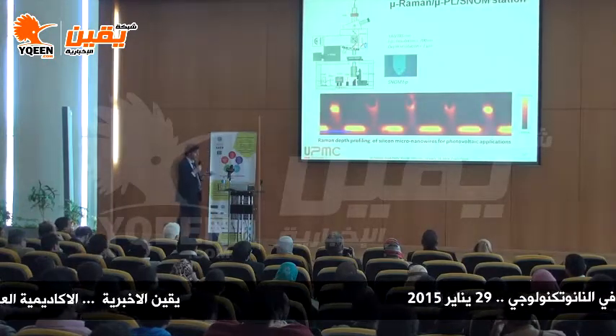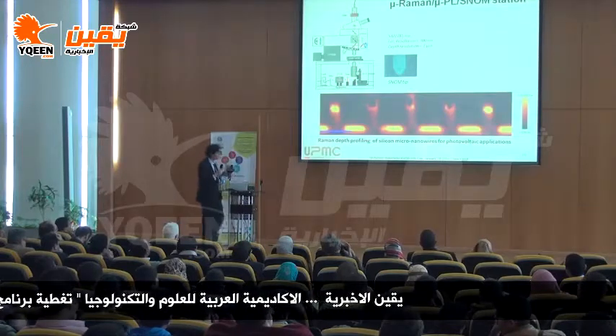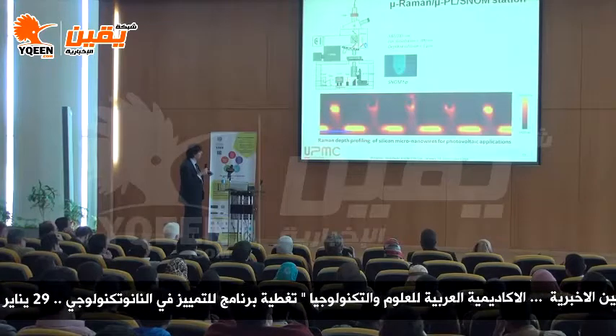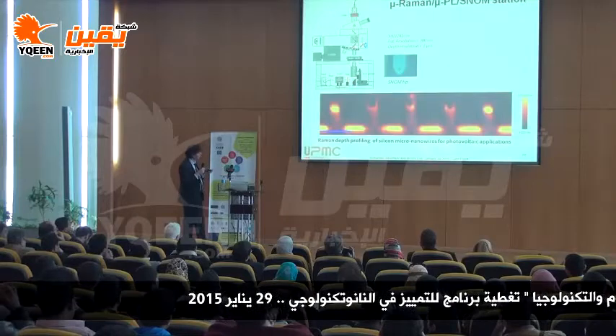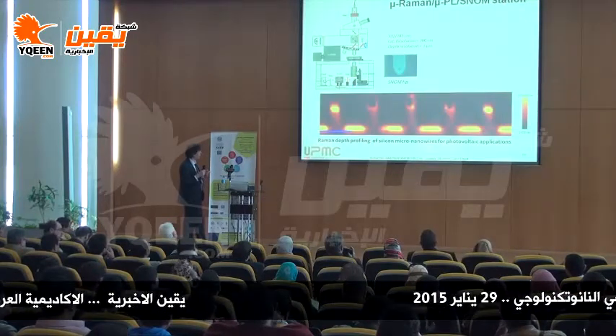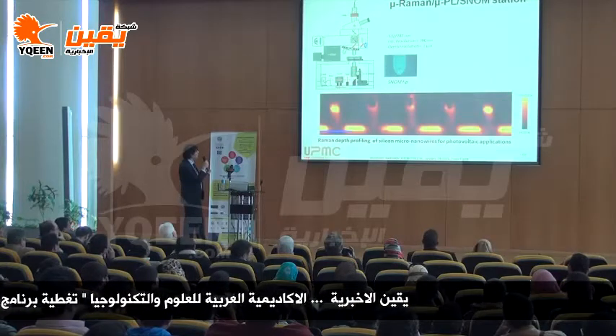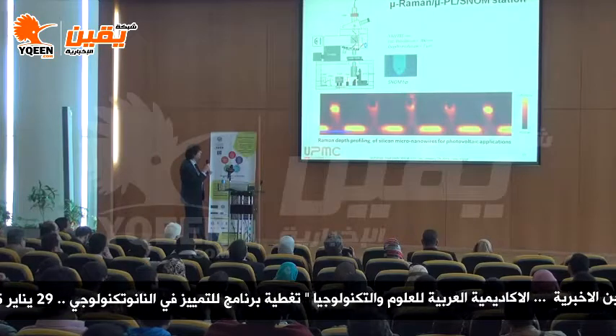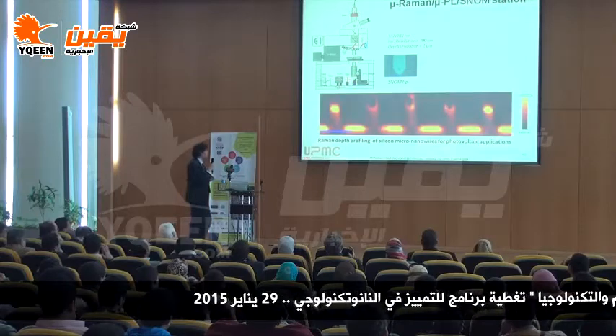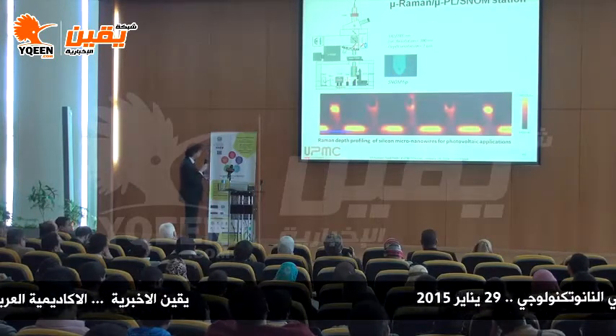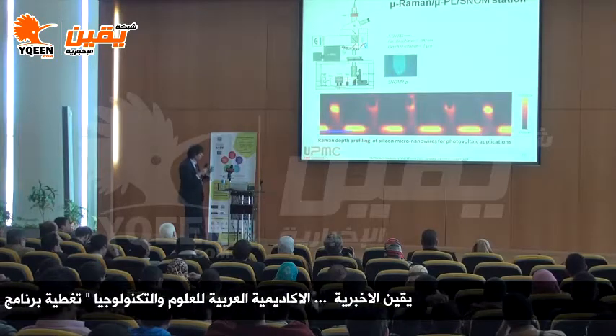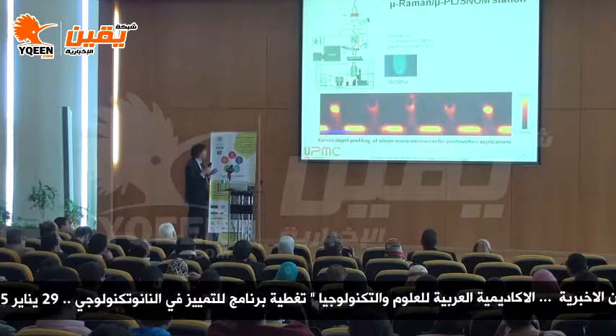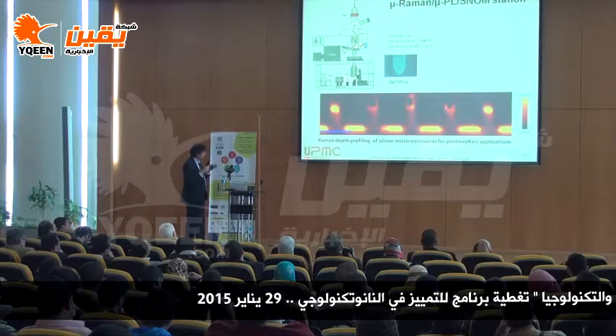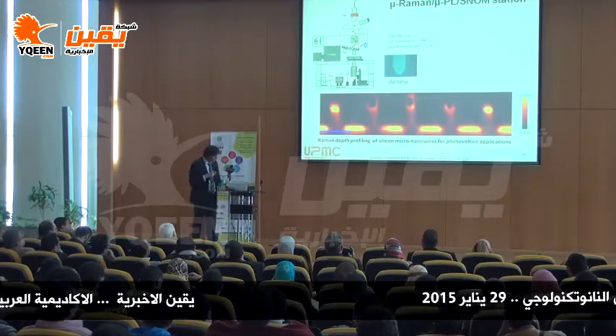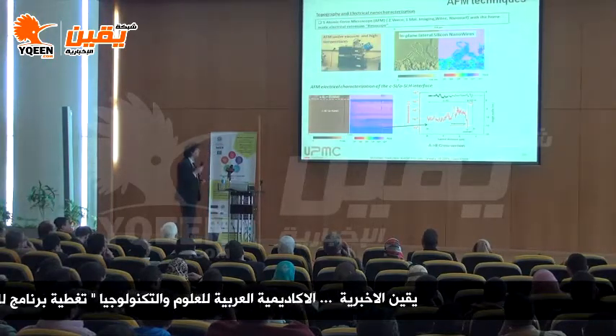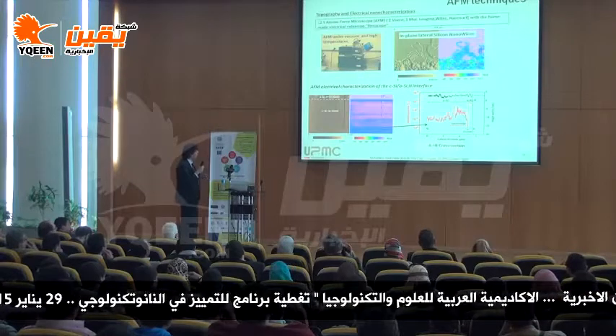Characterization tools: you can imagine that at this scale you need to develop and own some dedicated advanced characterization, basically with lasers and also motion stages that can move with submicron displacement. So here this is a platform that we use for running micro-Raman spectroscopy, photoluminescence, electroluminescence, and near-field optical microscopy. And that helps us to investigate submicron devices, whether it's for characterization of the material, so looking at the signatures of the materials, like with Raman, looking at defects with photoluminescence, and partly the topography and the plasmons with near-field optical microscopy.